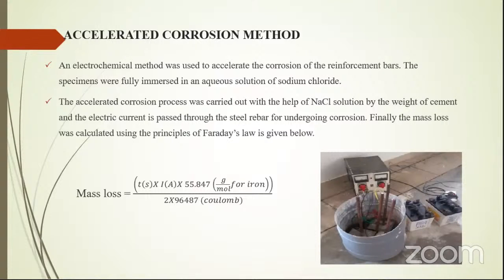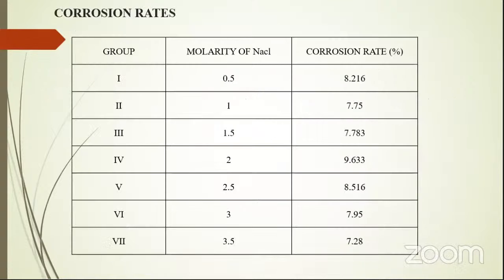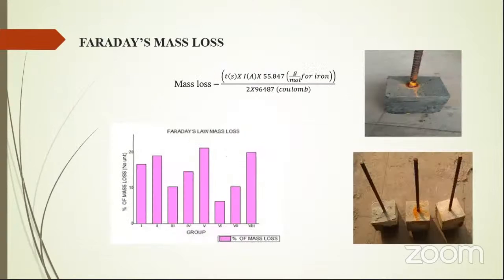The mass loss formula is about this. Corrosion rates: we use several groups, about 7 groups, and molarity of NaCl we added about 0.5 ratio. Corrosion rate is about 8.216, 7.75 percentage values. Faraday's mass loss. The mass loss formula is about this, and for several groups as x-axis and percentage of mass loss in y-axis, and we attain some graph.